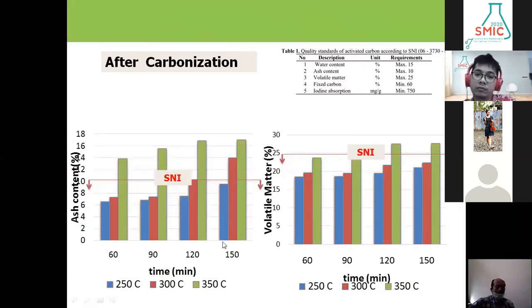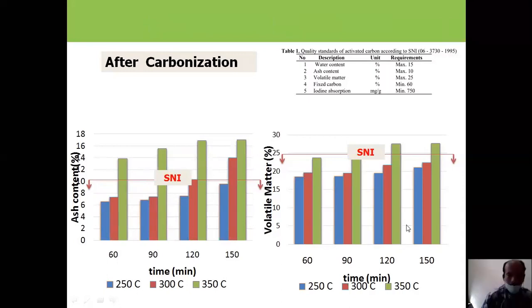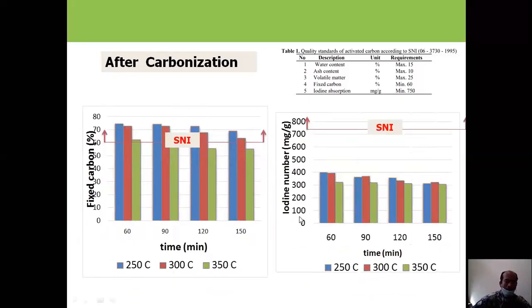15%. The ash content, we can see here most of them are below the required SNI standard, so it is good. But the best one we can see here is this blue one, at low temperature 250 degrees Celsius and for 60 minutes carbonization. And in volatile matter, carbonization at 60 minutes and low temperature 250 degrees Celsius is also good, and the volatile matter is also still under the required maximum number of SNI. And in the fixed carbon, we see again at 250 degrees Celsius, the blue one here is the best one.